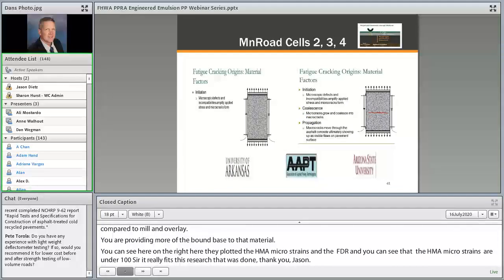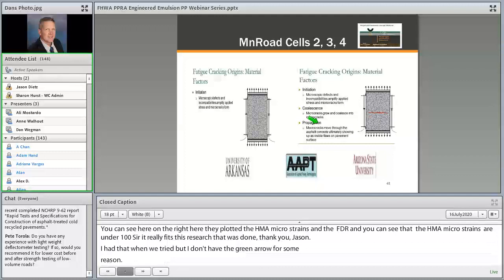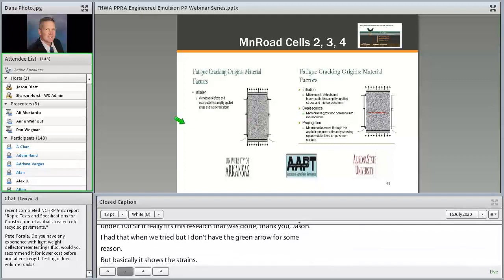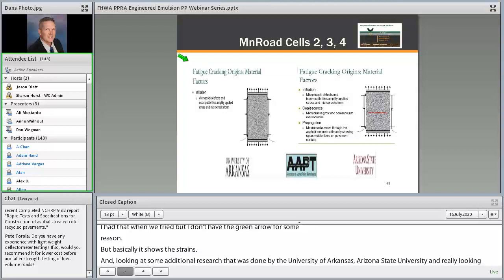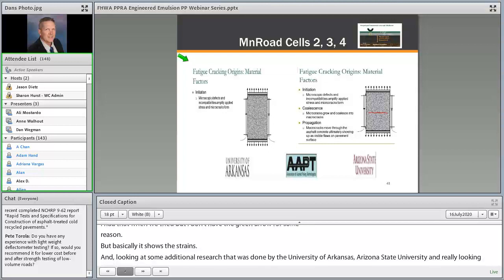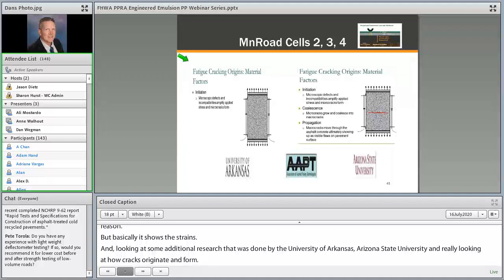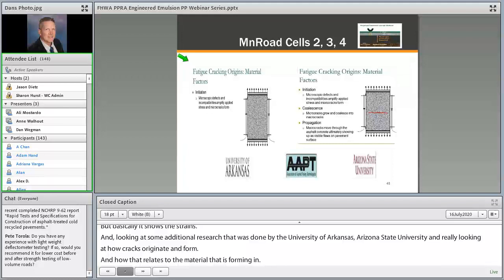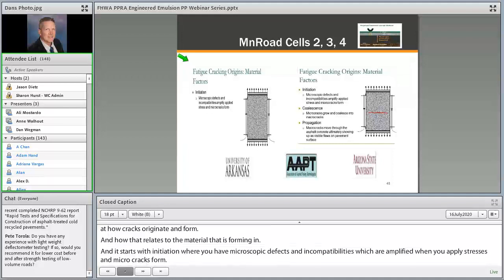And then looking at some additional research that was done by University of Arkansas, Arizona State University, and AAPT, really looking at how cracks originate and form, and how that relates to the material that they're originating and forming in. And it starts with initiation, where you've got microscopic defects and incompatibilities which are amplified when you apply stresses, and microcracks form. Kind of hard to see, but you can see the little red microcracks within that specimen there.